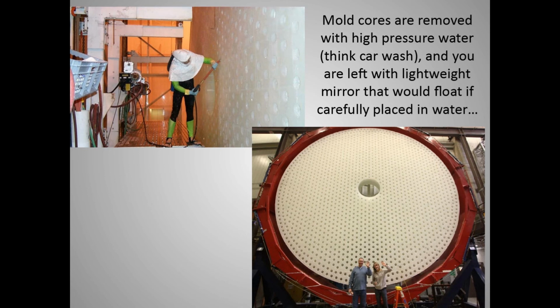And then they use high pressure water to remove the mold material. The soft refractories come off with high pressure water. You can pick at it with your fingernail or a screwdriver, but high pressure water is safer. And then you're left with a hollow piece of glass that, if placed carefully back down on water, would actually float. It's about 80% lightweighted, so if you put it on a body of water and put an outboard motor on it, you could have a little portable island. You could get it down to Chile that way by putting a motorboat on it and pushing it down.